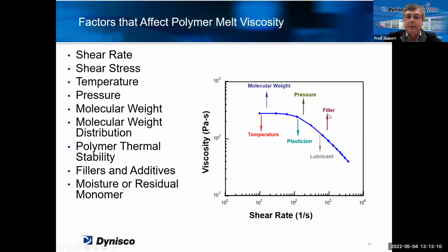And you will see also with fillers that it will go up. And of course, if you increase the temperature, the viscosity will go down. Also, if you put plasticizers or lubricants, it will go down. What the capillary rheometer will help you with is to define what will be the consequence of what you are changing in your polymers. Also, we are able to see, for example, moisture and residual monomers in the product. Moisture is really critical, especially if you think of PET, polyethylene terephthalate, or if you think also of polyamides.